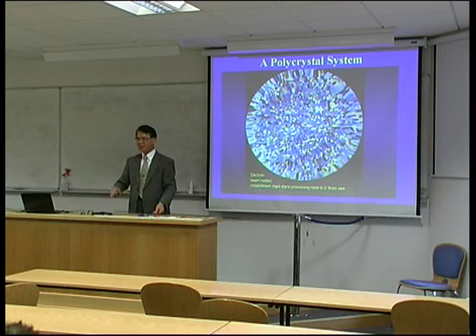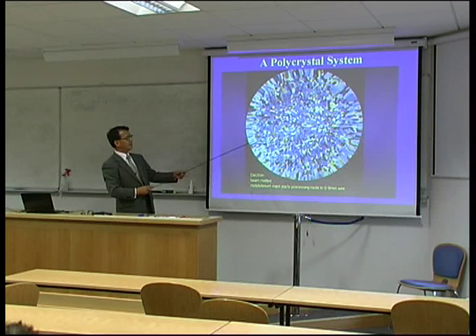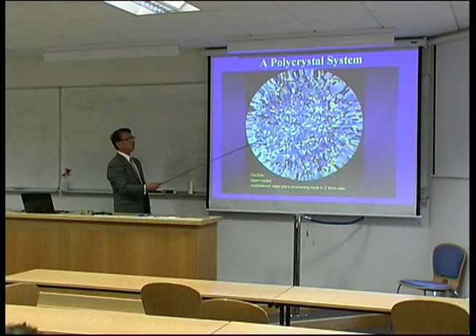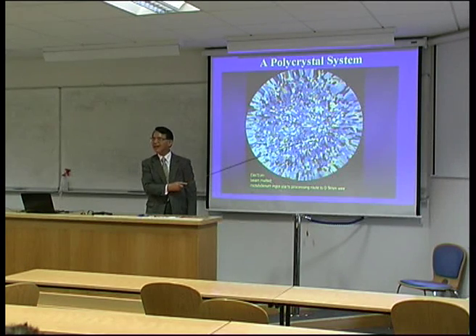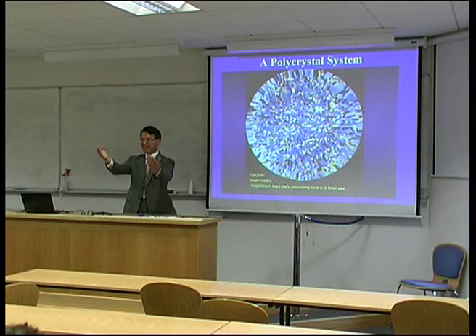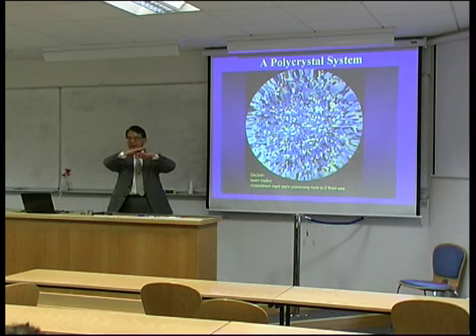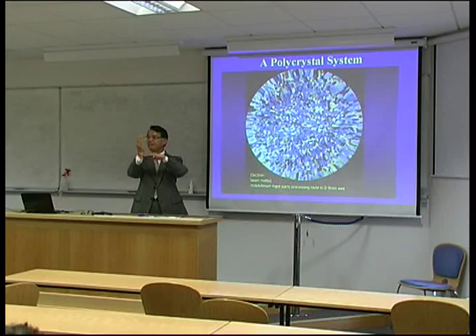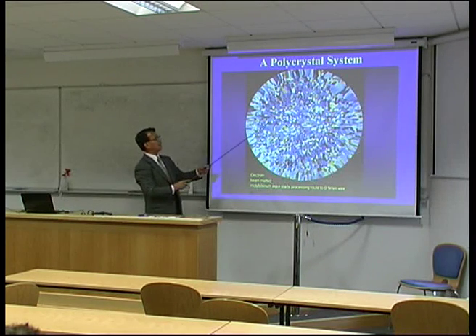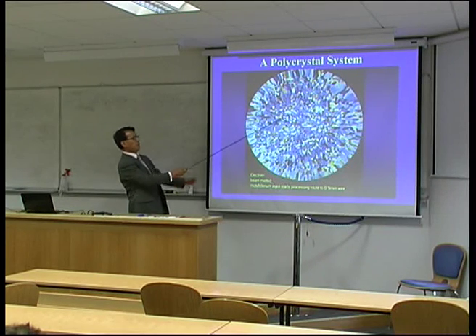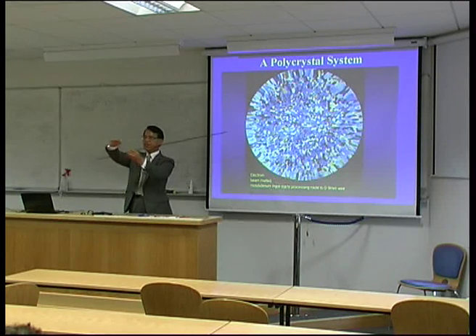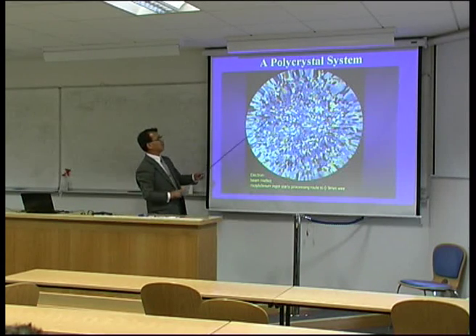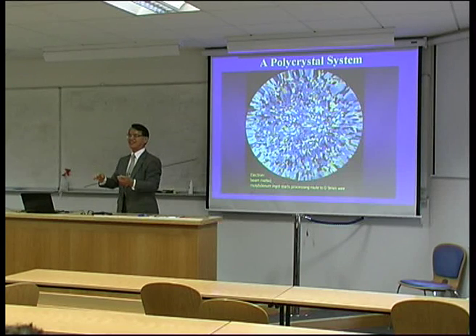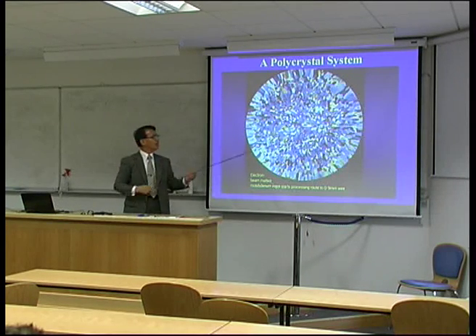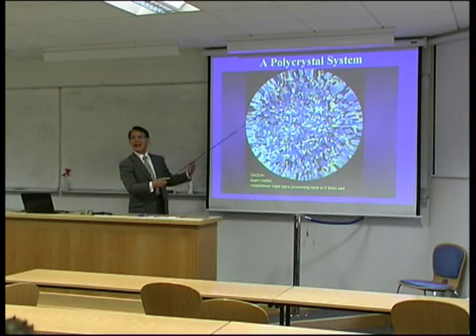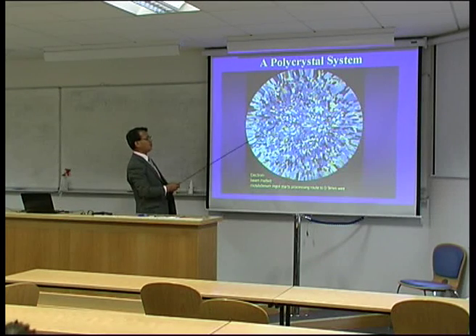But another important feature: as you see in the color, different grains show different colors. Why? Because this indicates the surface crystallographic orientation is different from grain to grain. So maybe the yellow grain has surface orientation 1-0-0, and the blue grain maybe 1-1-0, like this. So depending on the surface orientation, the color is different. This is another important feature.